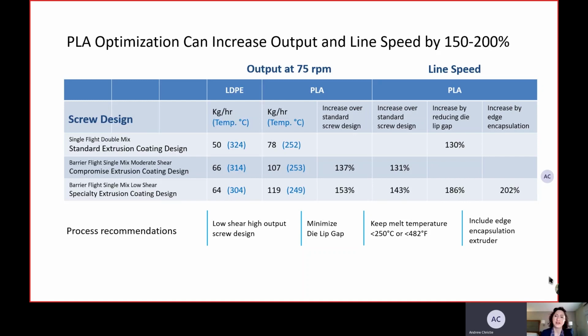And what can be done? You can reduce the die lip gap and you can have an increase in your line speed of PLA by reducing that die lip gap to change the drawdown. So that's something you can do right away today. And that got a 130% increase compared to without the die gap reduction.